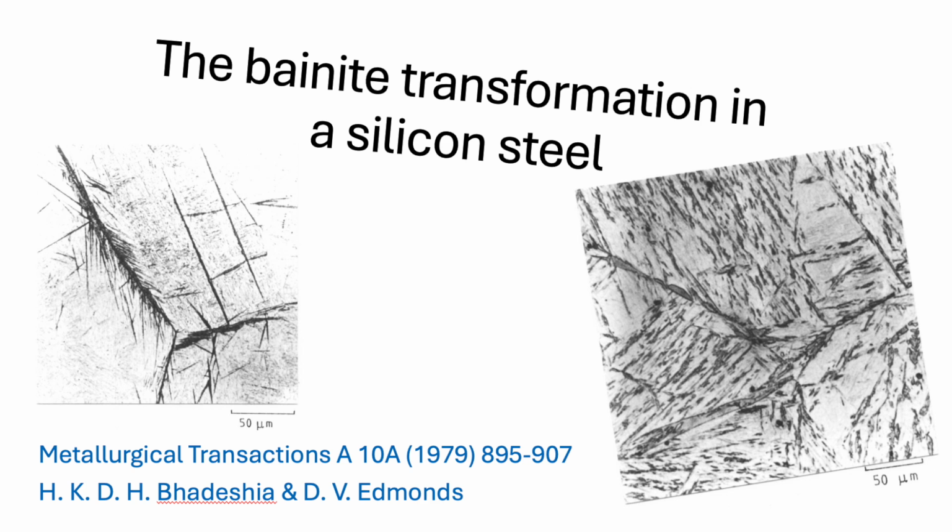Constant width. Did they measure it? They did. They estimated the width of these spikes to be roughly 0.2 microns. And this width seemed consistent, regardless of the exact transformation temperature within the LB range. 0.2 microns. That's tiny, but incredibly specific and constant. What does a constant width spike advancing into the austenite signify?